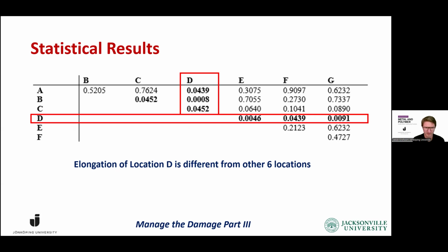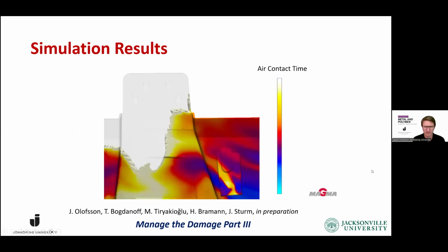And interesting here is the one point that sticks out when we apply this test. We do the combinations. We test, for example, A and B together, A and C together, A and D together, and you compare this. Position D, clearly, as marked here with the red lines, comes out. It's different from the others. The other ones, when you compare them to each other, there's not a statistically significant difference between those locations. So the failure behavior of the different positions is actually the same in all positions, even though you do see, if you take a look at just numerical average values, the underlying distribution is still the same. But location D is different.